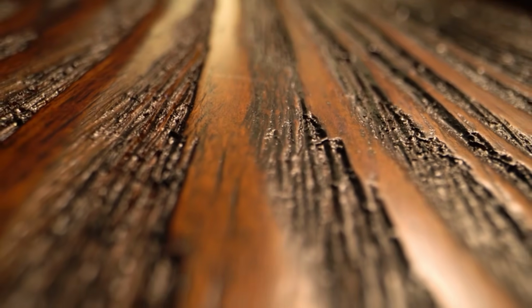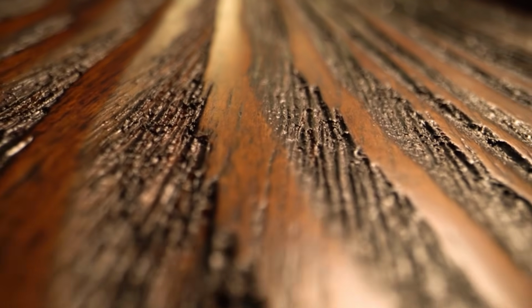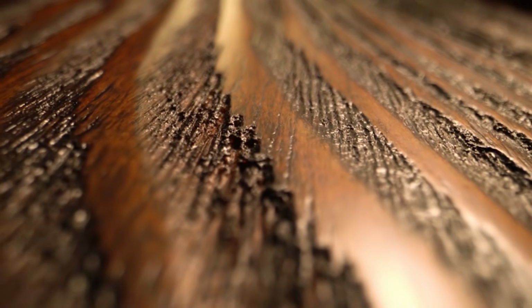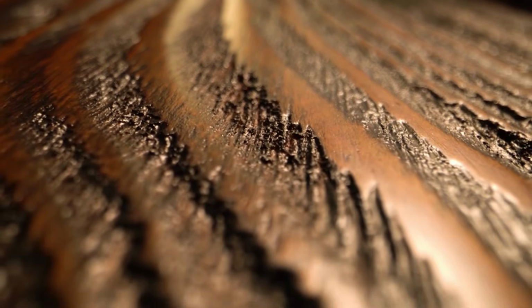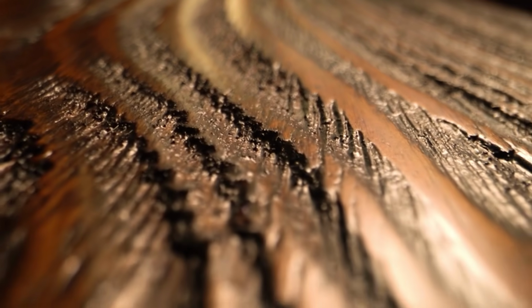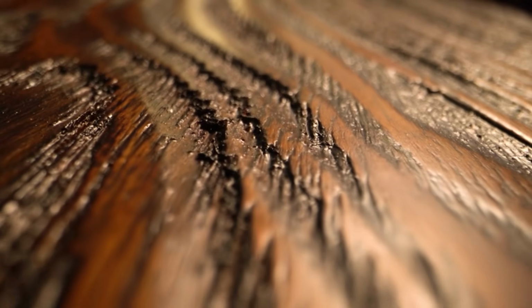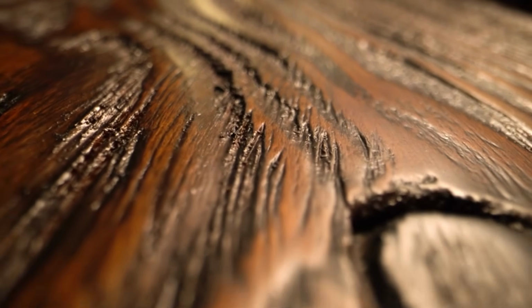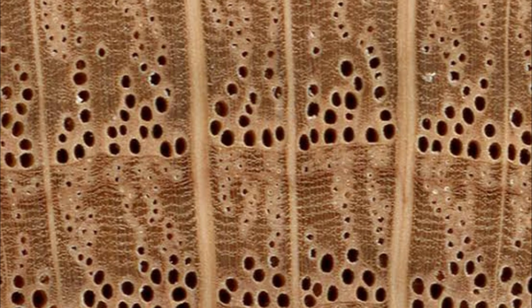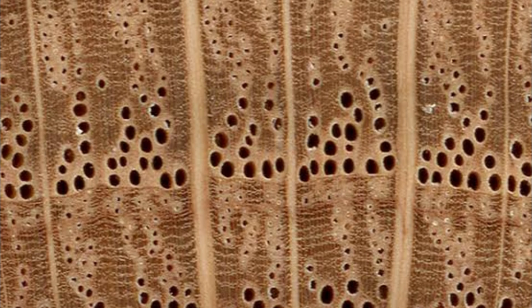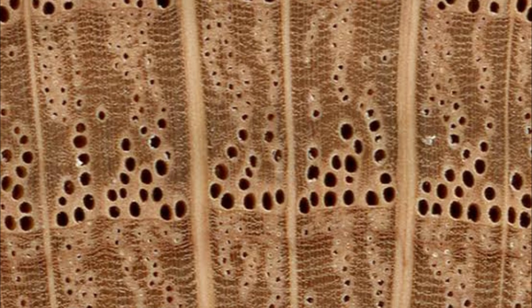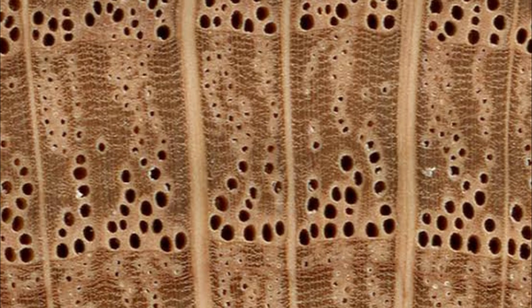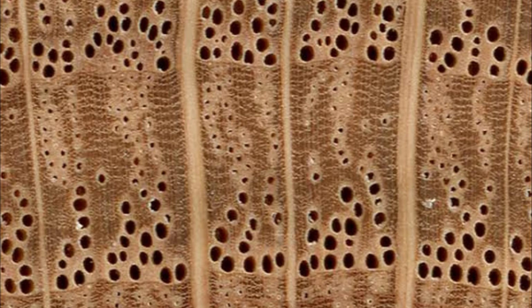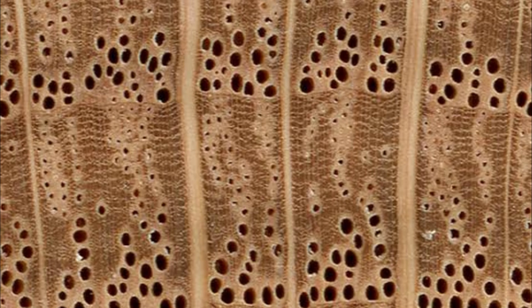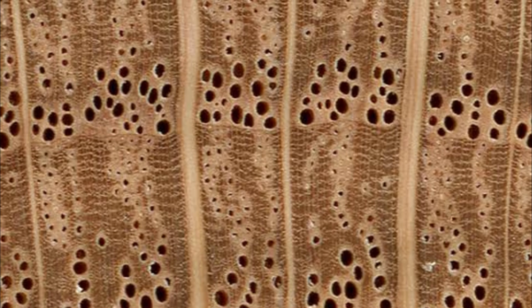The second property is density and tight grain. When wood has a specific gravity above about 0.6, water penetration slows dramatically. The cell walls are thicker, the pore spaces are smaller, and there's simply less room for moisture to move in and establish the conditions fungi need to thrive. The third property, and this one is critical, is the presence of tyloses. Tyloses are bubble-like growths that form inside the pore vessels of certain hardwoods as heartwood develops. White oak has them, red oak does not. That's why white oak holds liquid and red oak leaks like a sieve.